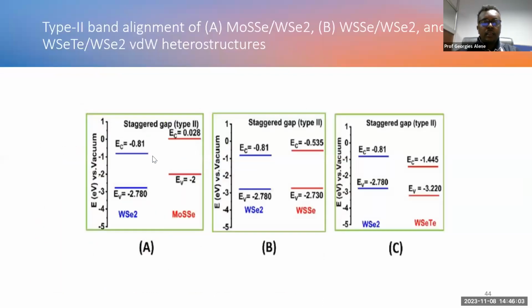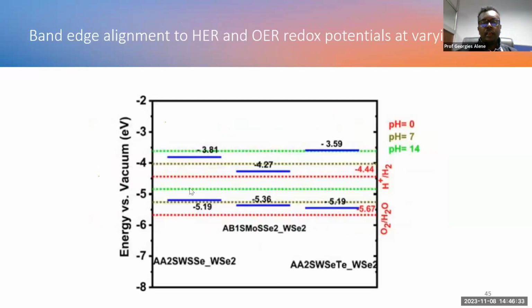And then we plot the band edge values of the two constituting monolayers of the heterostructure together. And as you can see, actually we have got again a staggered gap, which is type 2 band gap alignment, which is, because of the reasons I mentioned before, good for efficient separation of photogenerated electron carriers. And again, we investigated this material for photocatalytic application by plotting the band edge values together with the